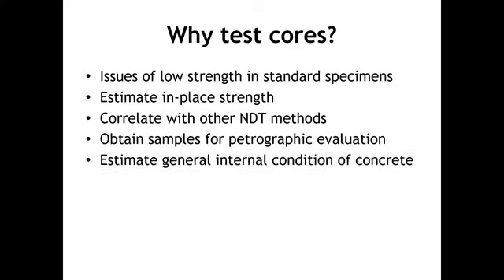But when you go for bridge structures, when you go for decks, obviously it is inevitable that sometimes you need to cut the rebar too. So it is better to use a rebar locator before going for cutting the core. The correction factor as per IS 516, if L by D is not 2, you can use. Normally once you take the core out, you have to trim it for the evenness on either side of it, and then do the ultrasonic pulse velocity as we discussed earlier.